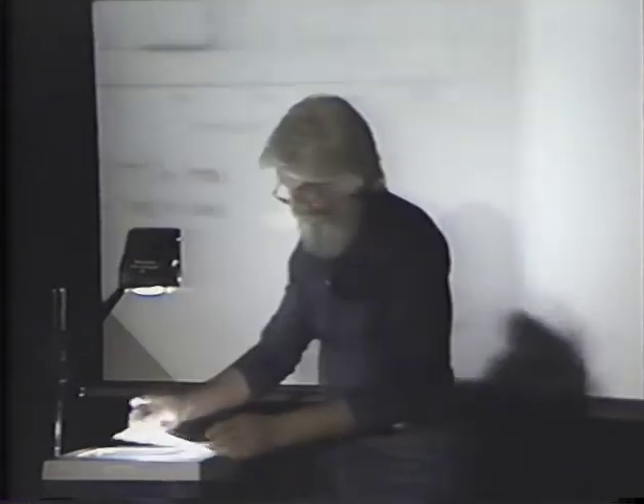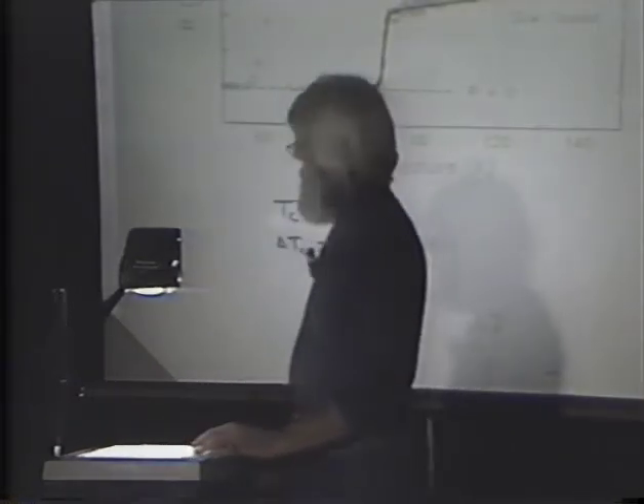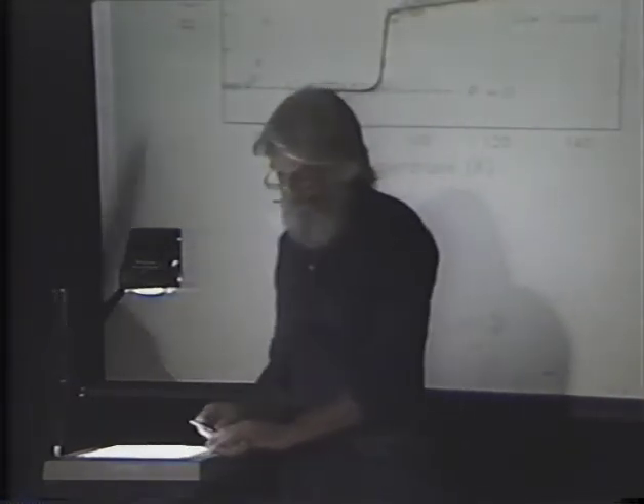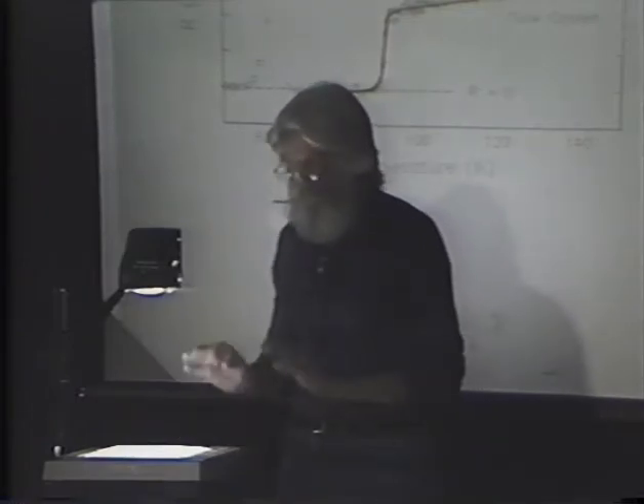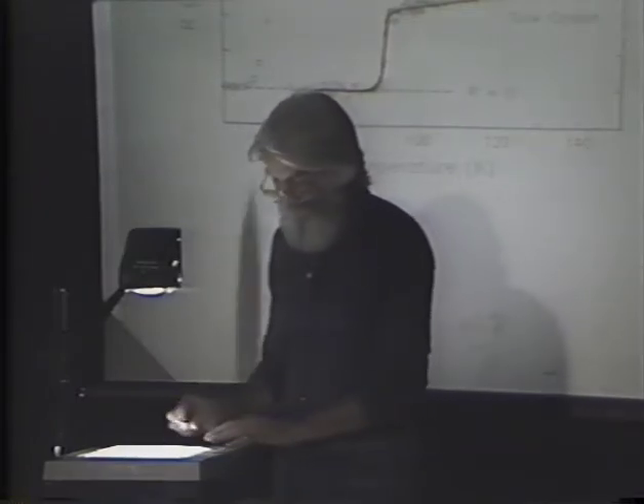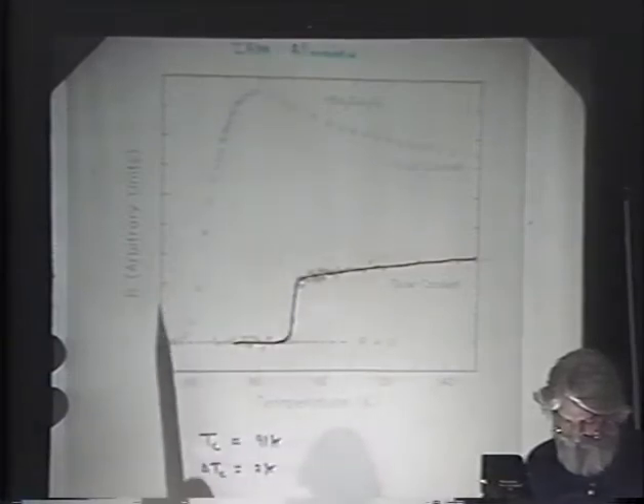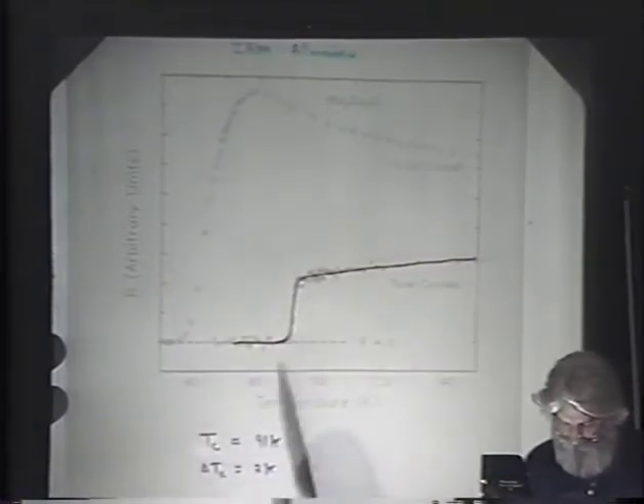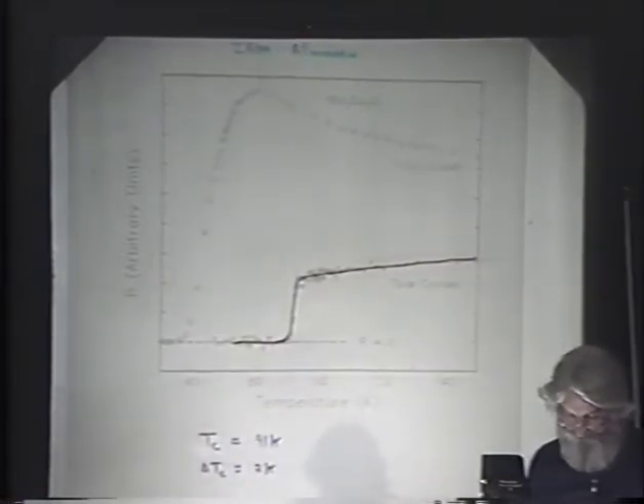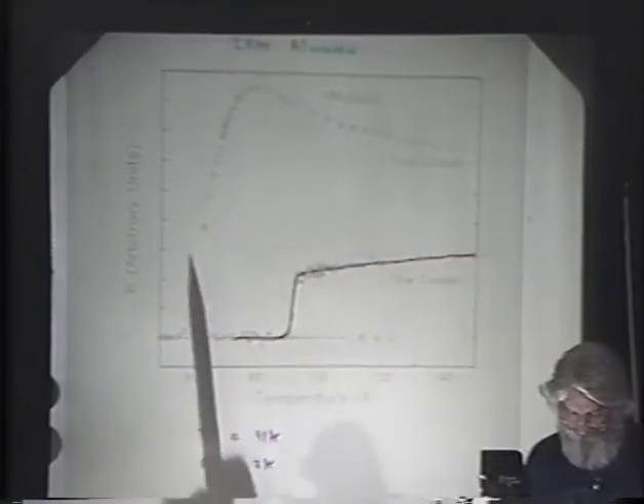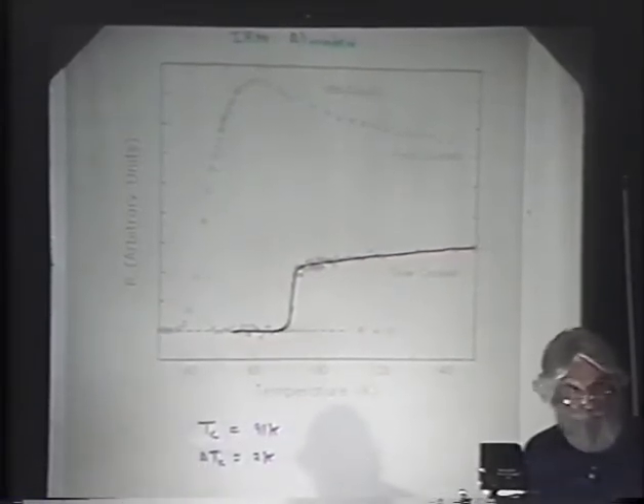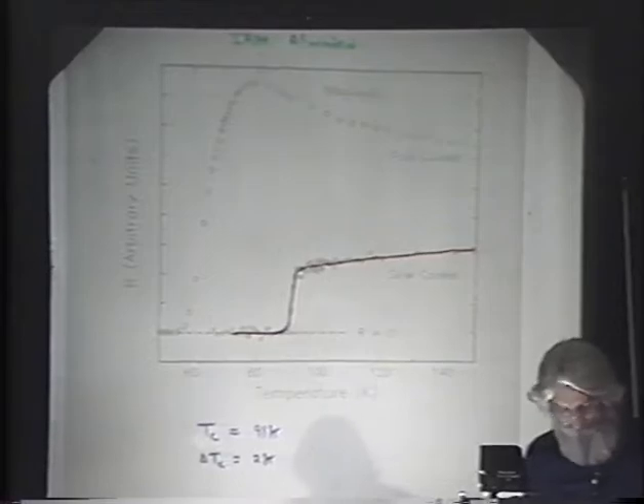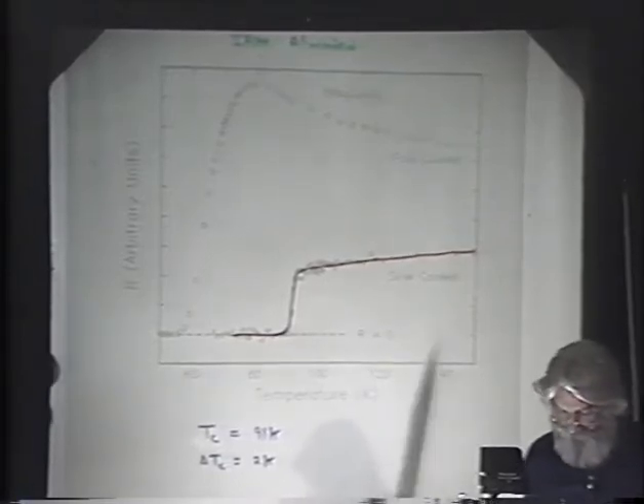Okay, just to show that we do superconductivity, here's a foil. Same sample, but annealed at different rates out of the furnace. This is fast cooling out of the furnace. This is slow cooled out of the furnace. You get two entirely different responses. Very percolative superconductivity for the fast annealed sample. Obviously, you're not getting oxygen equilibration. Slow cooled, it's very, very narrow.